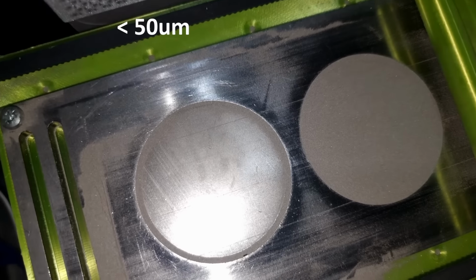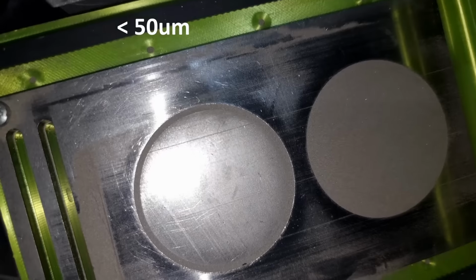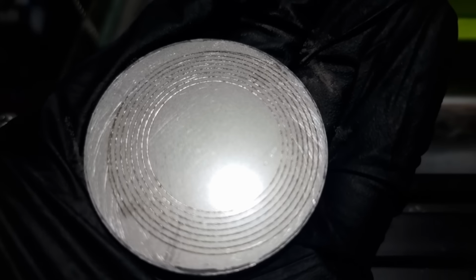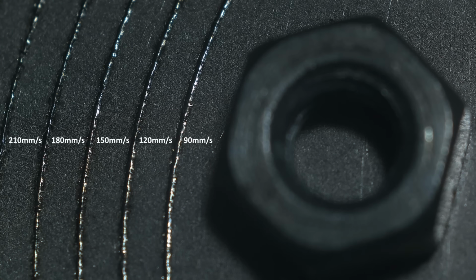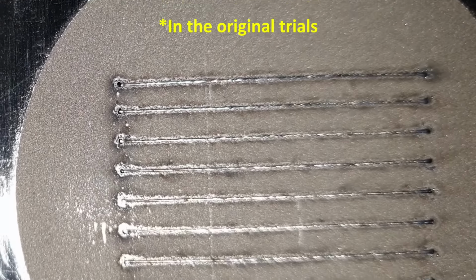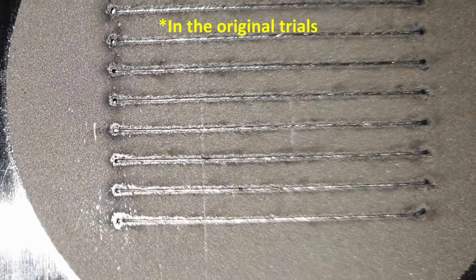So with the first powder layer now semi-transparent, I could produce cohesive tracks up to around 200mm per second, and noticeably without the vacancy in powder running alongside the deposited material. I had my guesses about why this was, but didn't feel that my theory regarding volume explained it, as the vacancy was wider than the track itself, but the answer would be revealed to me in time.